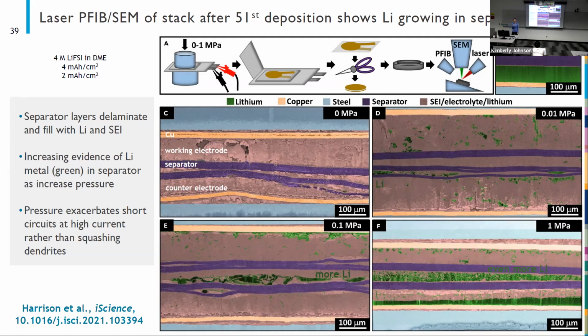And there's been a lot of work in the literature on this, even for lithium ion batteries, where inhomogeneous pressure distribution can cause a lot of issues. And so I think that's a really good point: as you grow these systems and scale them up, the pressure is likely to get more and more inhomogeneous, and that can lead to some problems.